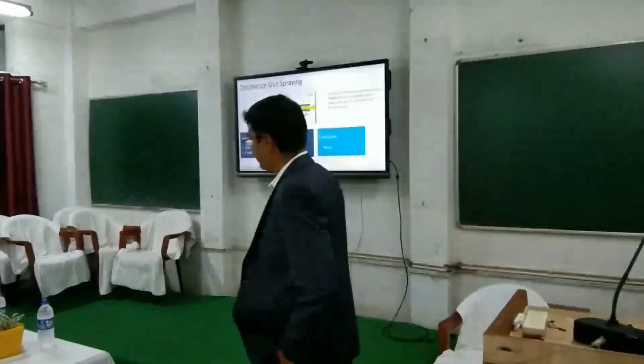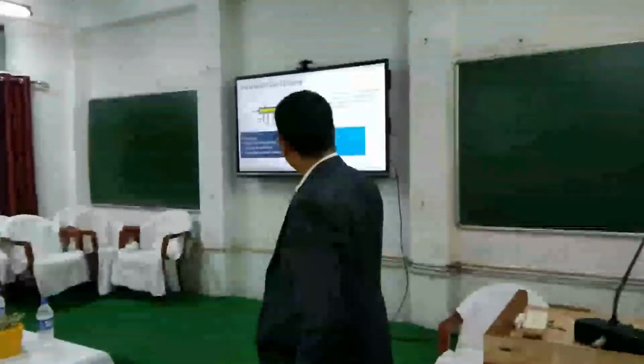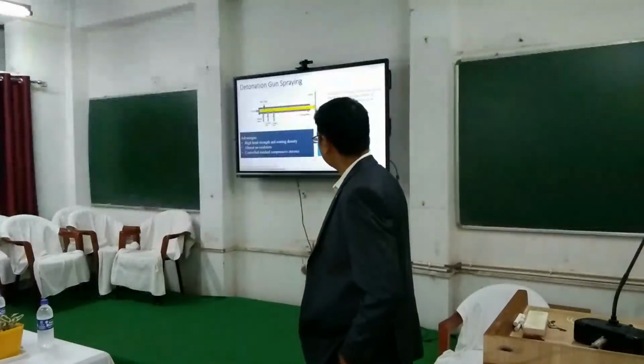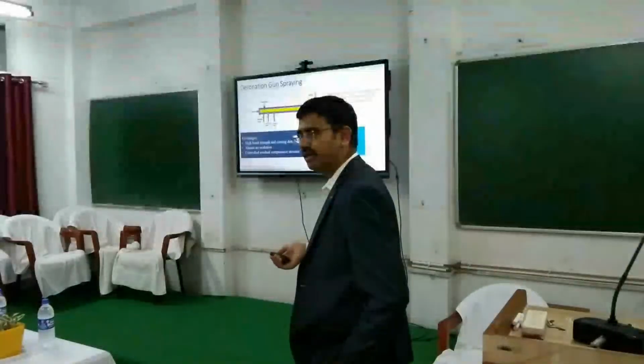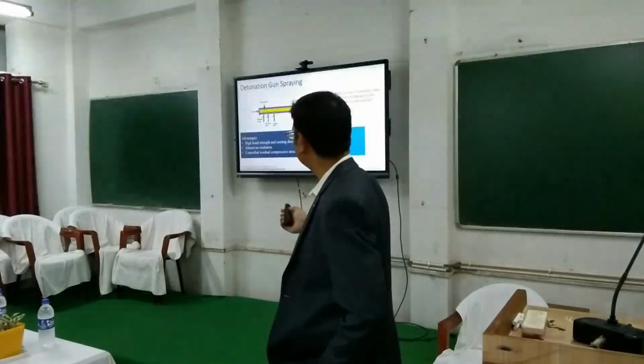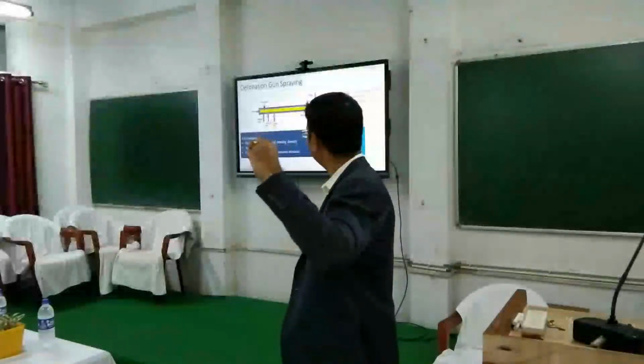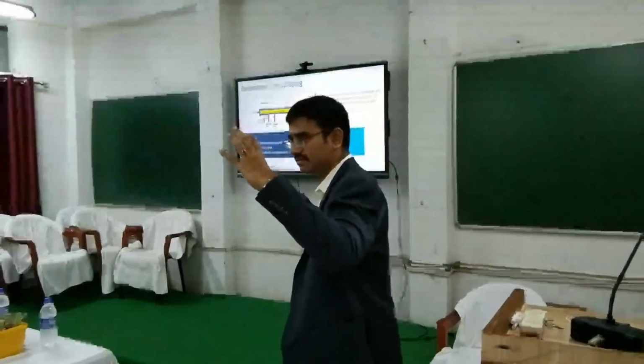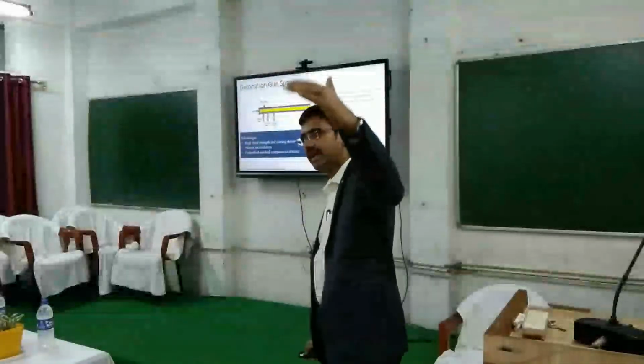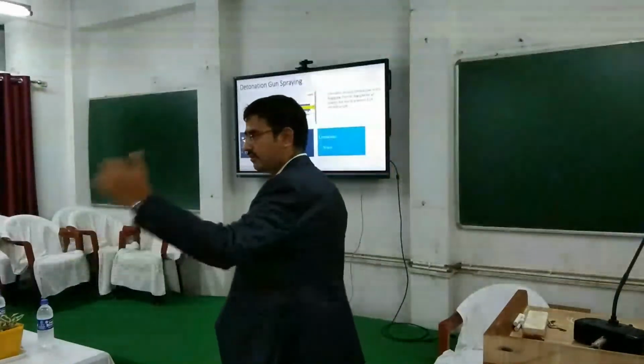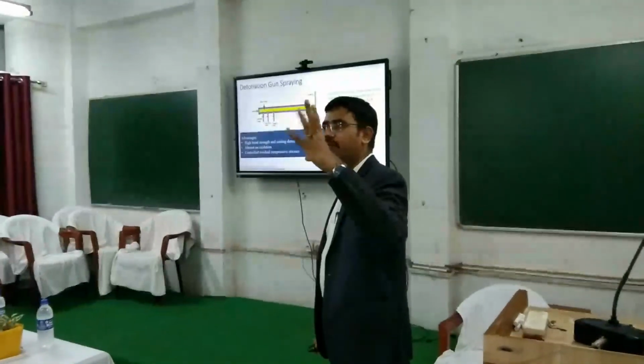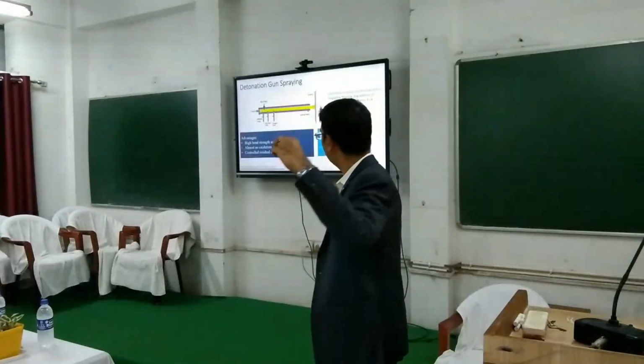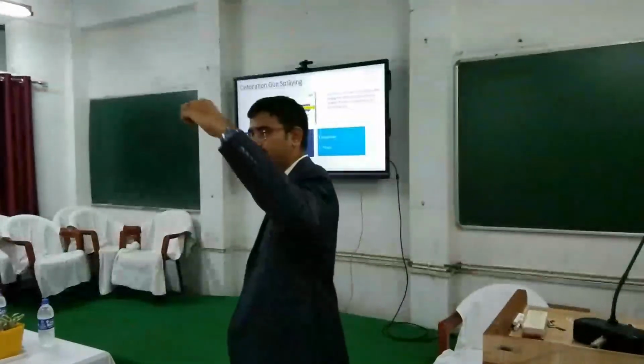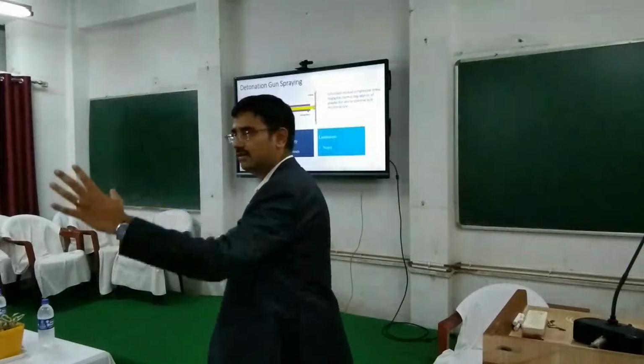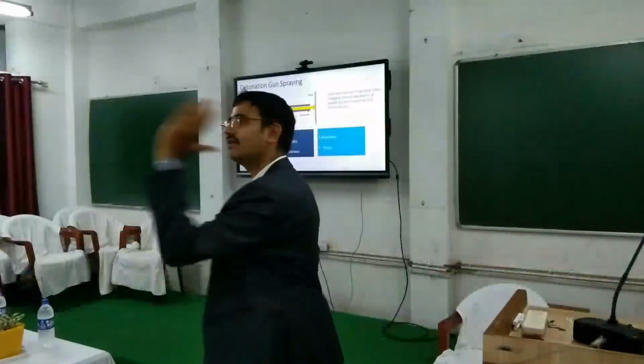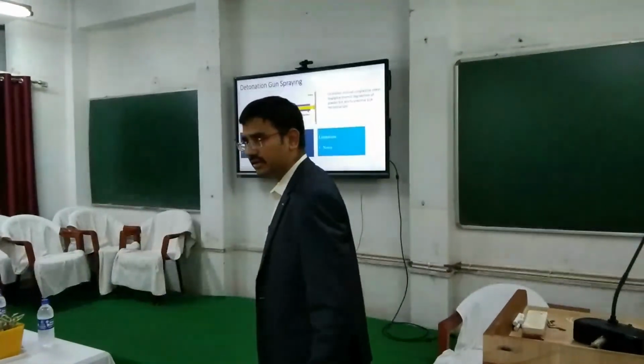Next is detonation gun spray coating. This typically is very rarely used. It is something like HVOF, but the main difference is that here you are giving the air fuel mixture in a pulse. There it is a continuous combustion, the gas is flowing, the coating is deposited. Here you are giving an air fuel mixture and then igniting it with a spark and giving a pulse. So the pressure wave carries your coating forward and it is deposited.